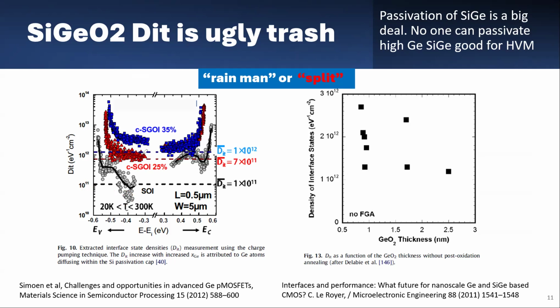And if you are here, forget it. Your device will never work properly. Your mobility is so low, you will lose all your advantage, right? So all these are no, okay? And it turns out it has a very strong dependence on the thickness. That's bad news too. I want a stable one. If it's a bad one, okay, that's fine. But it would change by 3x when it's very thin. And I want to be thin most of the time. So that's pretty bad news as well.